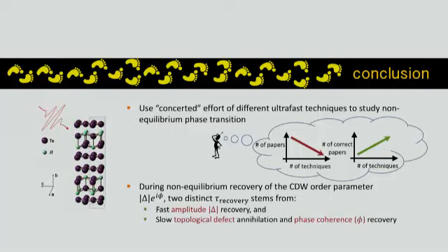But we did check the time scale of recovery at room temperature and at cryogenic temperature, and it's pretty much the same. Given that the TC of this material is more than 600 Kelvin, in terms of phenomenology, room temperature and say 10 Kelvin are pretty much the same. And it's pretty much a second order phase transition.